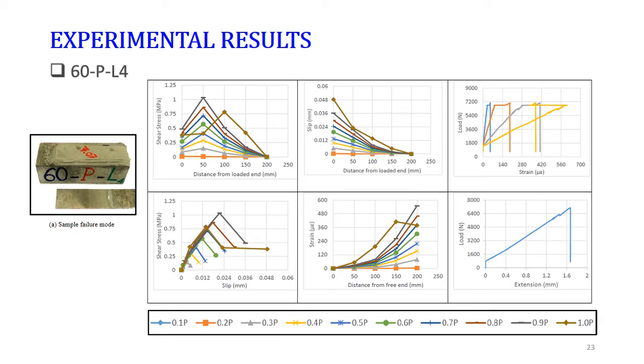Well, the first one on the top left shows you the shear stress versus the distance from the loaded end, and you can see that the shear stress increases up to a certain length, and then after that starts to decrease. The second one shows you the relationship between the slip and the distance from the loaded end, and the slip is maximum at this end and approaching 0 when it's approaching the other end.